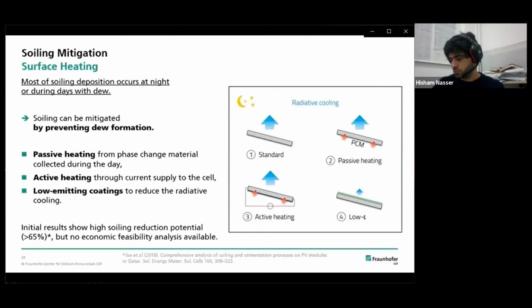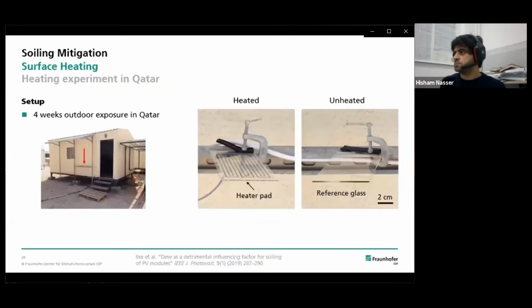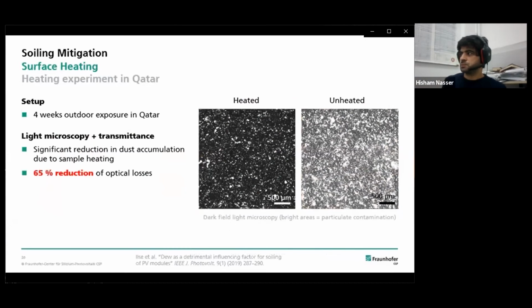using low emitting coatings. And to evaluate this, we conducted an outdoor study in Qatar for 4 weeks, using a set of samples with one glass coupon being heated by a heater pad and one unheated reference. After 4 weeks, we found a significantly reduced surface coverage for the heated coupons, which resulted in about 65% reduction of the optical losses.